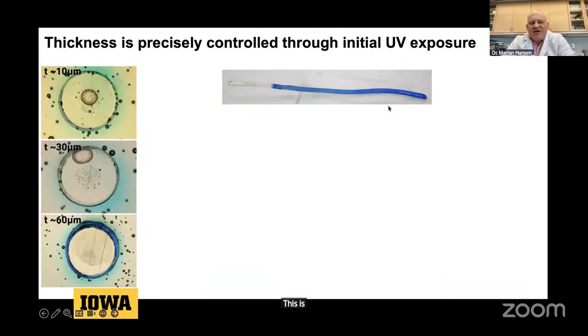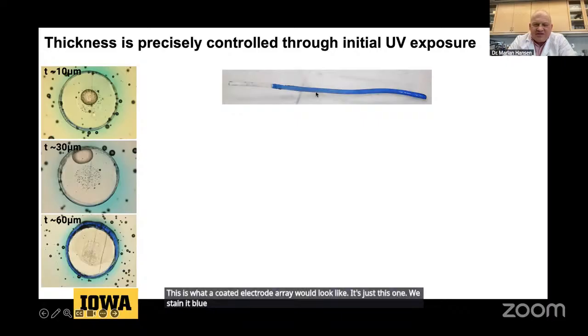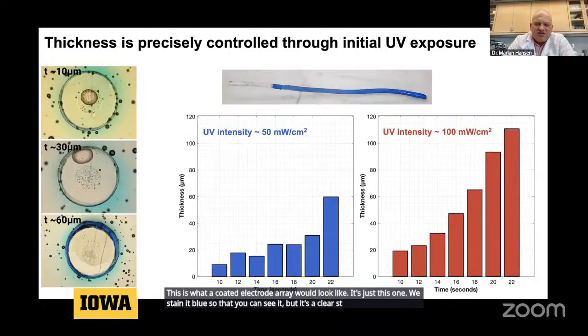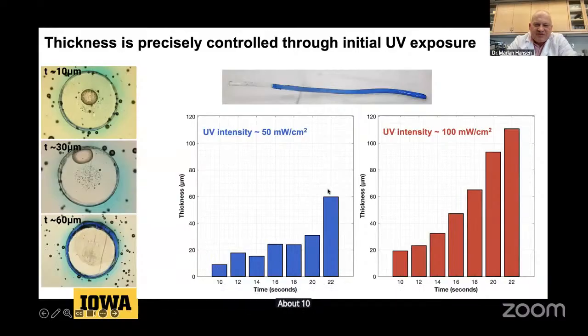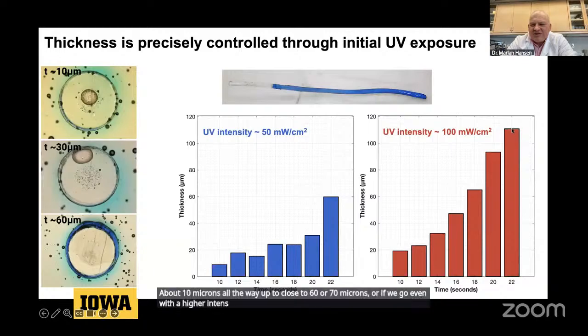This is what a coated electrode array would look like. We stain it blue so that you can see it, but it's a clear stain. We can control the thickness just by controlling the initial intensity of how much light we use and the duration of how long we do it. So we can have thicknesses that go from about 10 microns all the way up to close to 60 or 70 microns. Or if we go even with a higher intensity light, we can go up to over 100 micron thickness in our coatings.